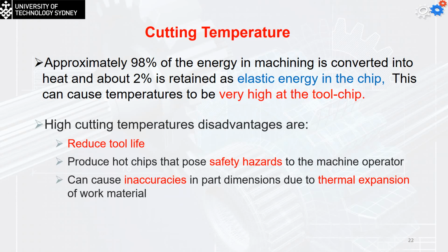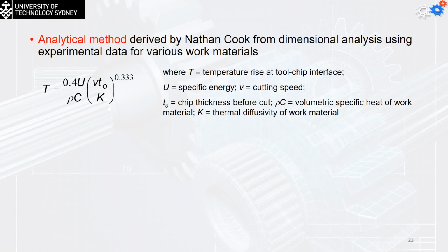High friction, high temperature generated, the part will be expanded. I did the dimension of the cutting according to my design. I leave it to cool down, it's shrunk. So we can use an analytical method derived by Cook to check what will be the temperature generated during the cutting process. So the temperature is equal to 0.4 U divided by rho C, multiplied by the velocity and original thickness divided by K, all to the power 1/3.